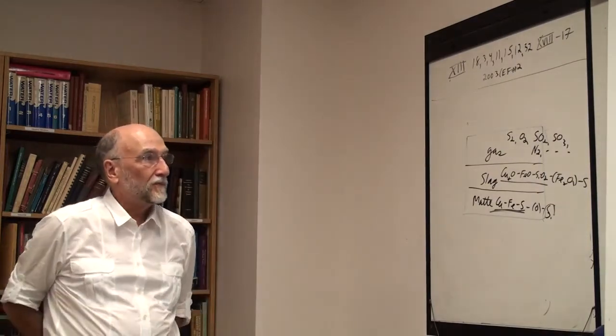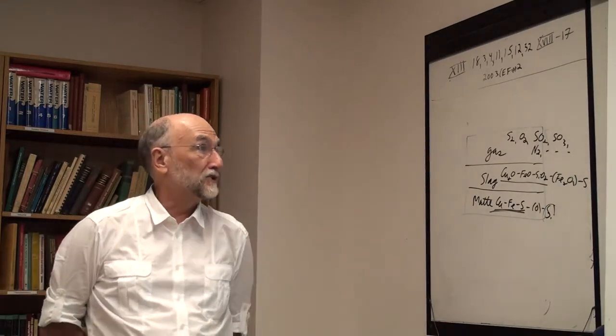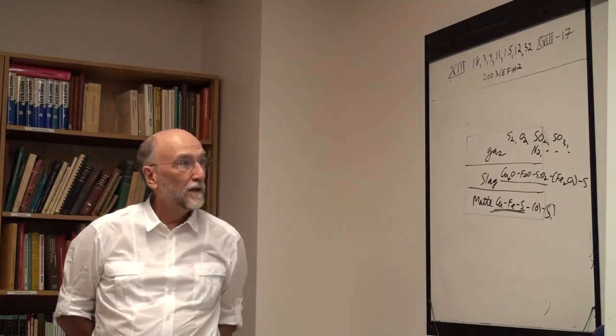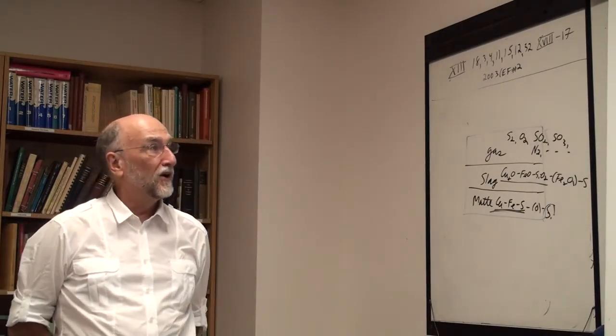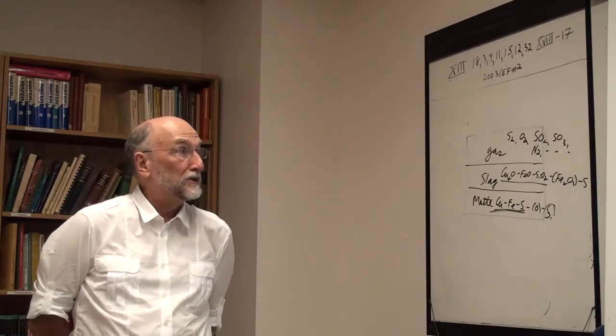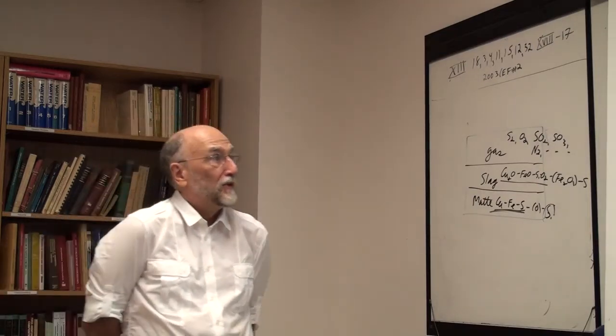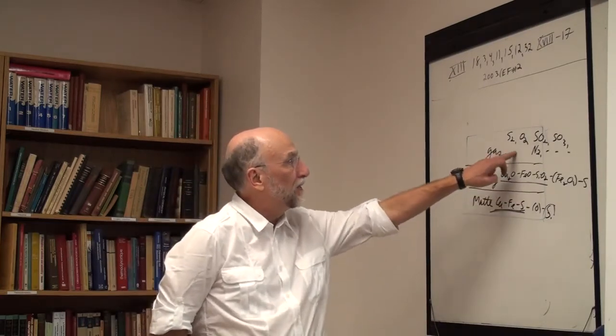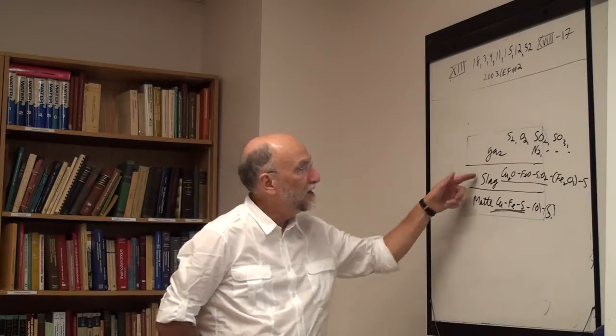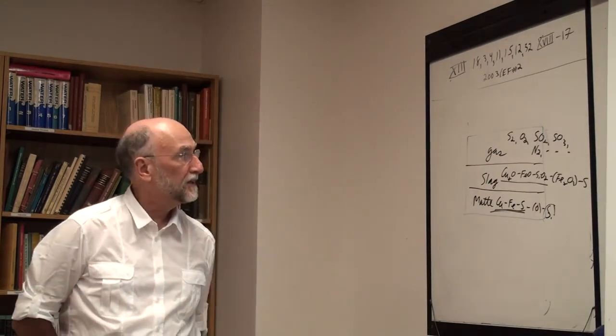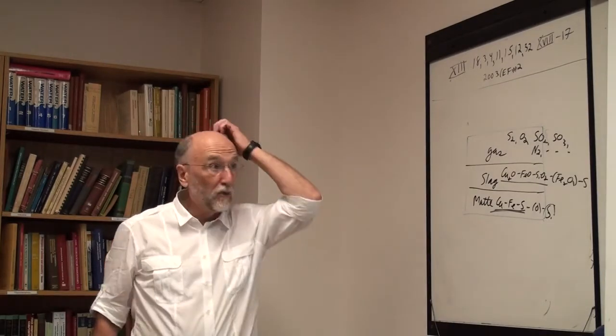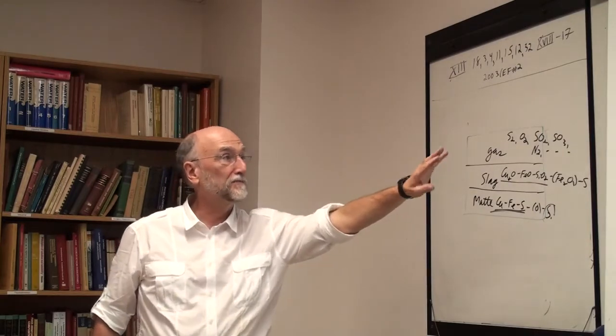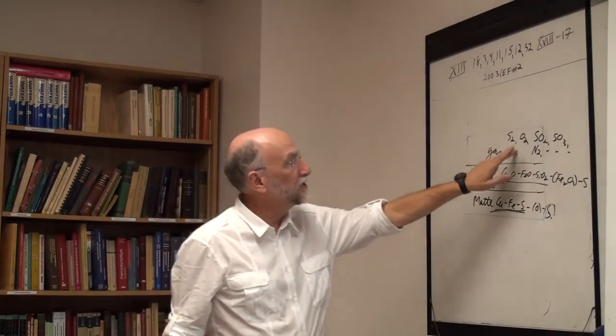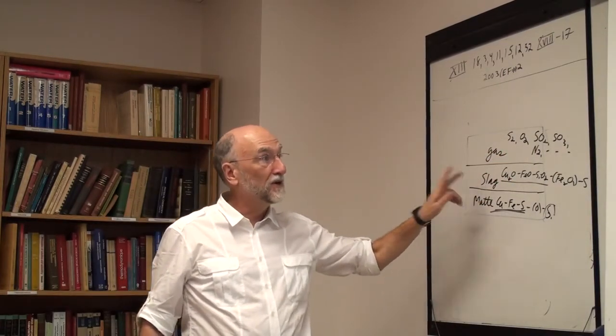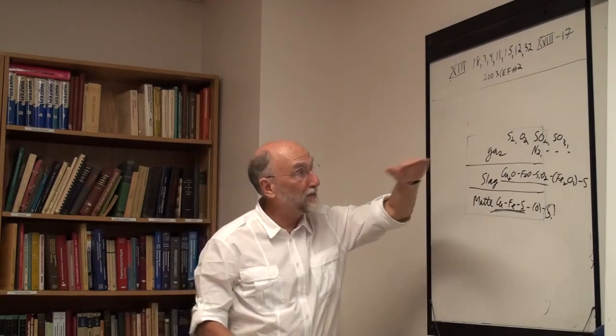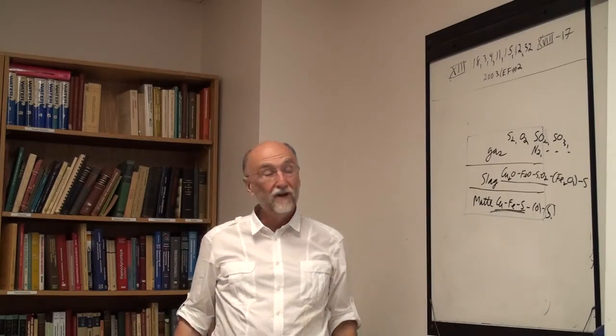Okay, so the temperature is constant and the total pressure is 1 atmosphere. Now I phrased this two ways. The first way, all the thermodynamic properties are in principle known, and an engineer says that, at least in principle, if he measures the partial pressure of SO2, and the partial pressure of oxygen, and the sulfur content of the slag, then he can calculate the composition of every phase. In other words, that's enough to fix the degrees of freedom at 0. If temperature, total pressure, SO2, oxygen content, and the sulfur content of the slag are known, then the number of degrees of freedom has gone to 0. At that point the composition of every phase is fixed, calculable if you had all the properties.